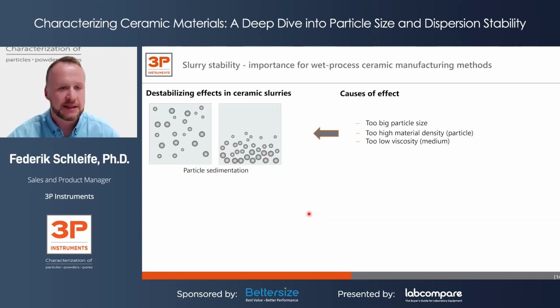So last but not least, let's discuss how slurry stability might affect the manufacturing of the final workpiece. Slurry stability is of interest and is important when it's about the wet route for the shaping process in ceramic manufacturing. As we already showed on the slide before, the density of ceramic raw materials is relatively high, and especially compared to water, it is maybe 5 to 6 times the density of water.